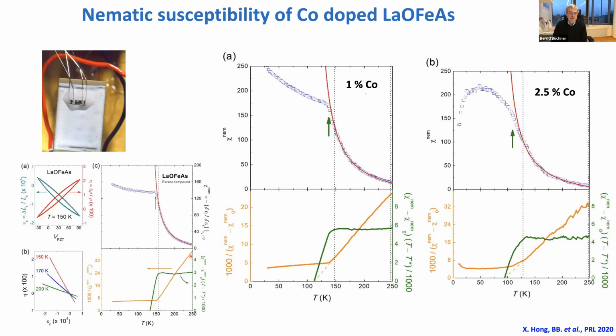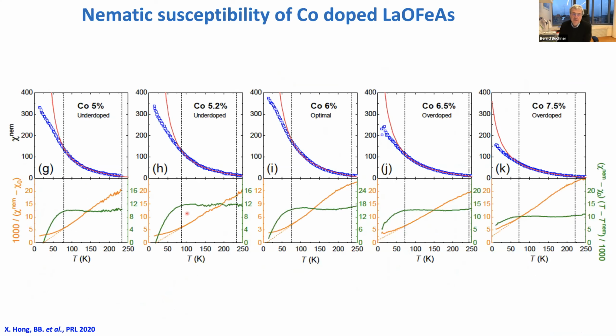That's all well established for the other systems. Here you can see that this Curie-Weiss fit is not so bad. And you can extract the Curie-Weiss temperature, which is close to whatever, 130 Kelvin for the parent compound. And this you can do now for all these doping concentrations. So this Curie-Weiss fit is more or less working also for doped crystals. What you see then is that this Curie-Weiss temperature becomes smaller. And then you can follow this behavior up to very high concentrations. So this is now underdoped, and we go to overdoped samples.